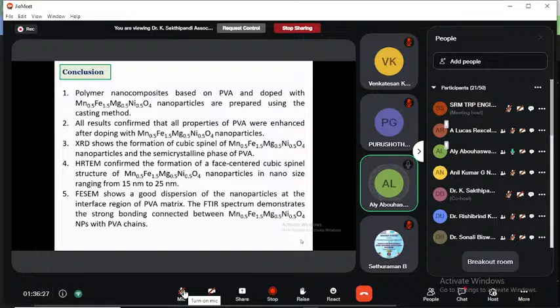XRD shows the formation of cubic spinel ferrite nanoparticles and the semicrystalline phase of PVA. The transmission electron microscopy confirmed the formation of face-centered cubic spinel structure of manganese, iron, magnesium, nickel nanoparticles in nano size ranging from 15 to 25 nanometers. Scanning electron microscopy shows a good dispersion of the nanoparticles at the interface region of the PVA matrix. In addition, the FTIR spectrum demonstrates the strong bonding between the spinel ferrite and the PVA chain.